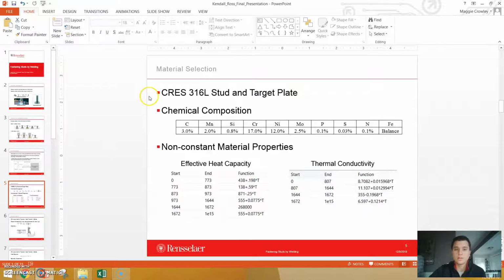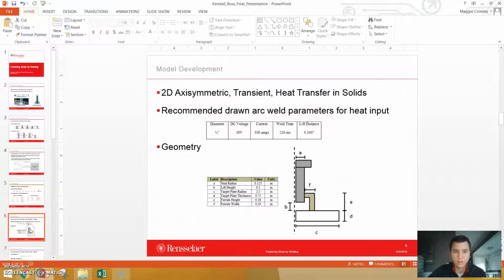To create my model, I selected corrosion resistant 316L stainless steel for the stud and the target plate, so they're both comprised of the same material. This is the chemical composition of the stainless steel, as well as some non-constant material properties that I used, the effective heat capacity and the thermal conductivity. Note that for both of these, there's a specific value for the melting range, which is 1644 Kelvin to 1672 Kelvin. That's just to show that there are different properties during that melt phase, which is obviously true.